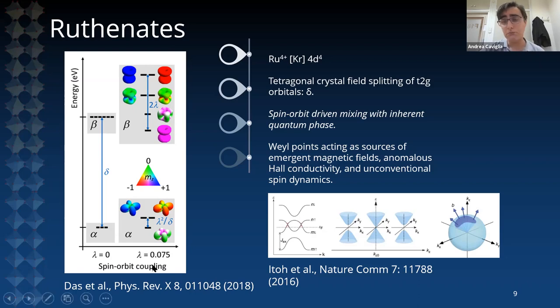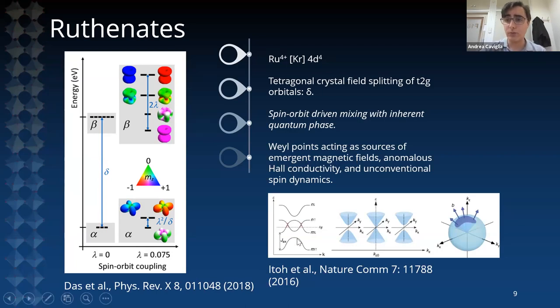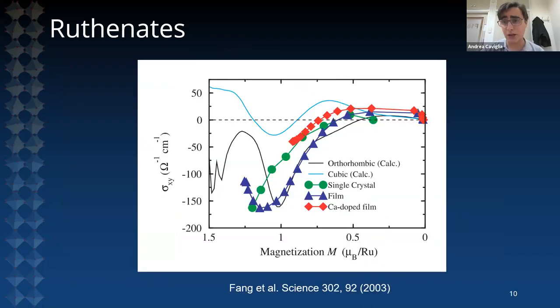The representation of spin-orbital states is a mixed state with an inherent quantum phase. This is the ideal condition to obtain non-trivial geometric structure of your wave functions. Indeed, in bulk strontium ruthenate, when time-reversal symmetry is broken, the conduction band splits and you find Weyl points in the system — sharp sources of Berry curvature. As such, they act as sources of an emergent magnetic field, anomalous Hall effect, and also some unconventional spin dynamics.